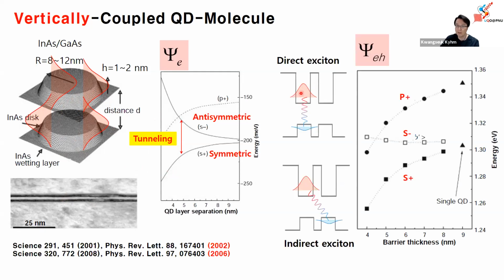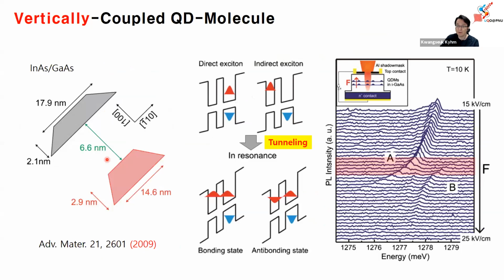If you want to study optically, for example excitons, you have to consider not only direct excitons, but also indirect excitons, which consist of an electron and hole from different dots. Again, by changing the barrier thickness, the dot-to-dot distance, you monitor the energy levels from the microphotoluminescence. Several years ago, the Dresden group nicely reviewed optical studies of vertical quantum dot structures, based on tunneling regimes and wave function overlap, and they observed anti-crossing by applying an external DC field. So they basically change the slope of the potential.